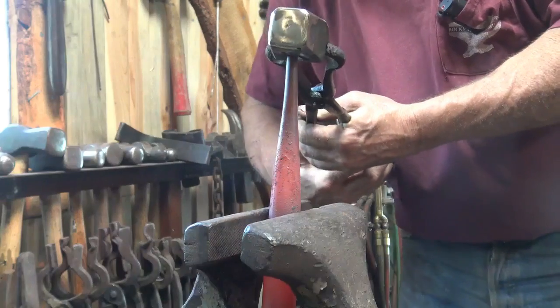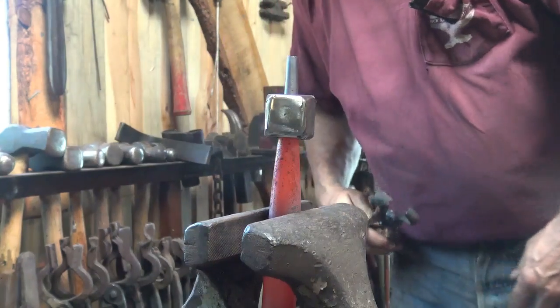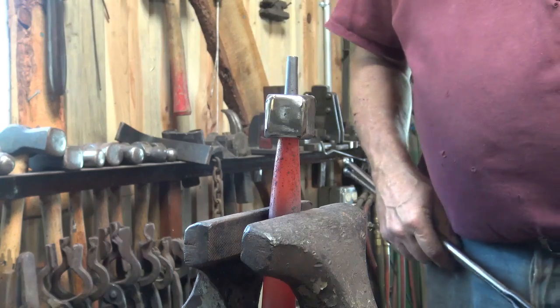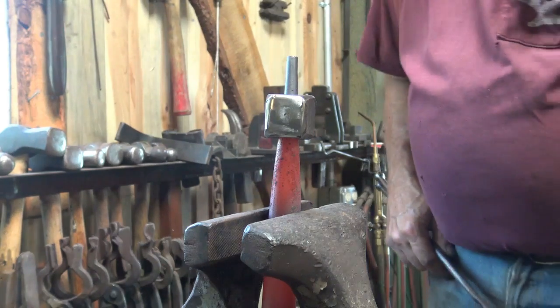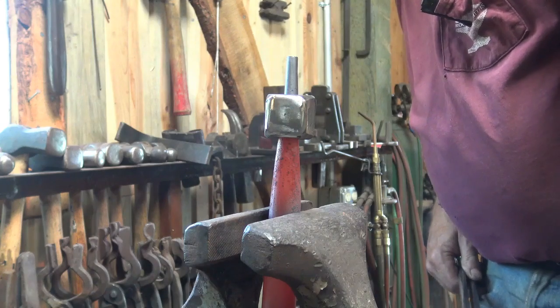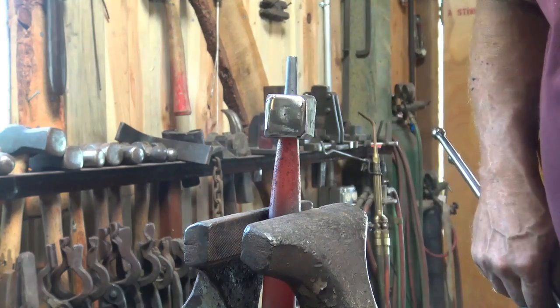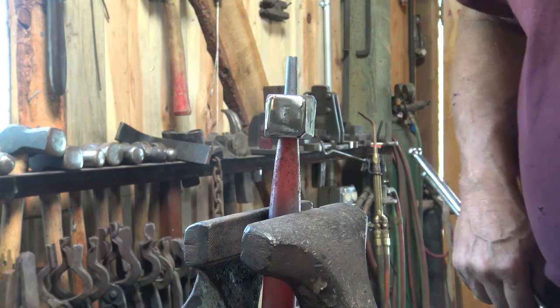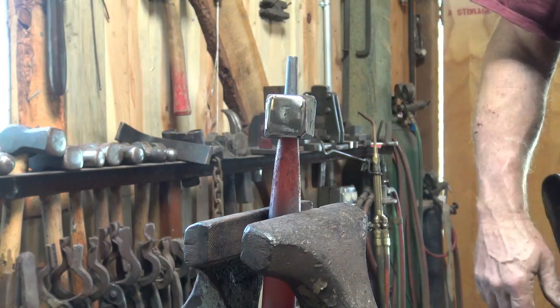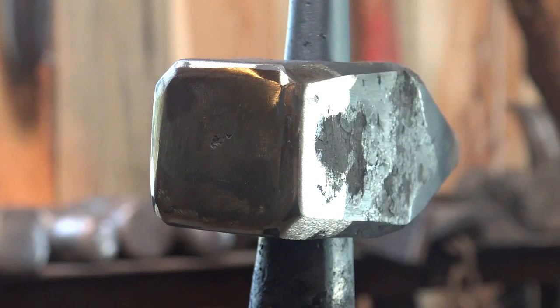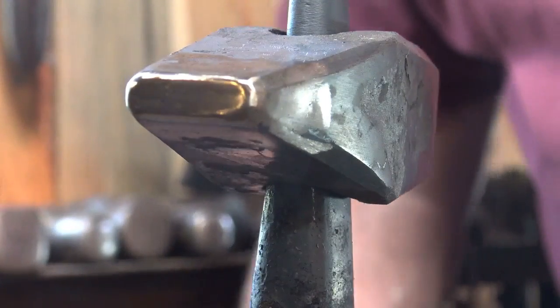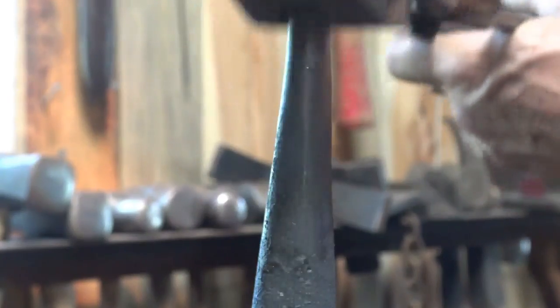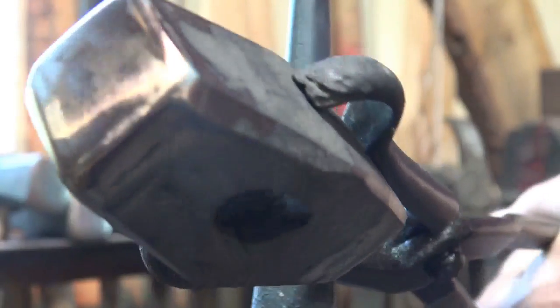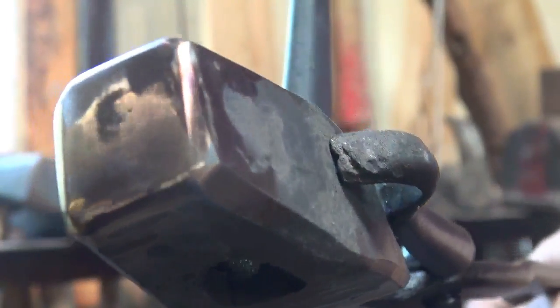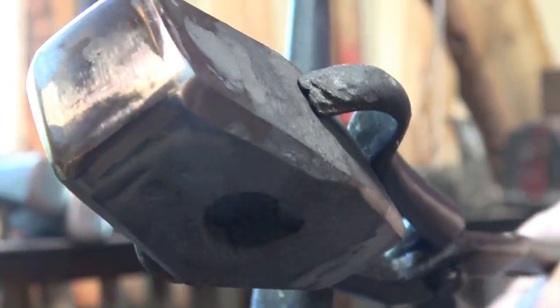Flip it over every now and then. You want it to heat as evenly as possible, and keep an eye on both the face and the peen. If the peen starts to show color change earlier than the face, you may need to quench just the peen. What we're looking for is a bronze to a peacock color. It's kind of hard to see the color change on the camera, but that's turning a nice straw to bronze. So that's almost where we want it.